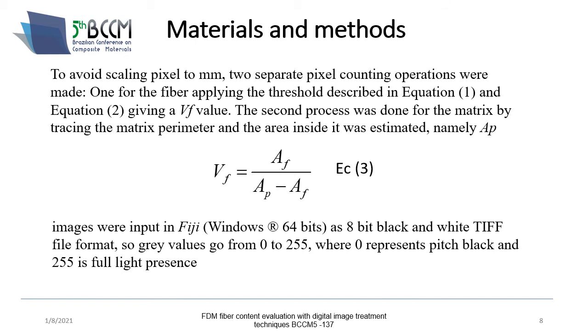To avoid scaling pixel to millimeter, two separate pixel counting operations were made. One for the fiber applying the threshold described in equation 1, and equation 2 giving a volumetric fiber fraction. The second process was done for the matrix by tracing the matrix perimeter, and the area inside it was estimated, namely AP, and the volumetric fiber fraction was calculated using the total area of the fibers divided by AP minus AF.